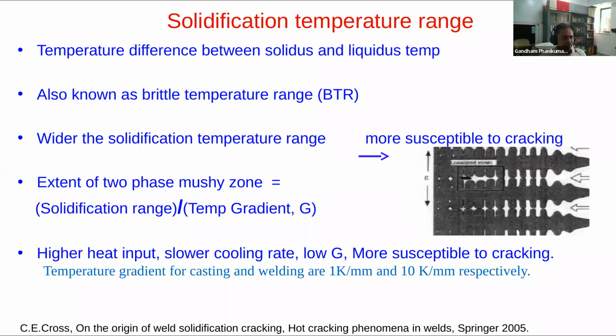Okay, and if you look at the origins of the RDG criteria, they are all talking about how the liquid that is trying to feed the solidifying region is suddenly getting its channel cut off. So that kind of bridging leading to the channel being cut off is the reason why the crack can nucleate, because all metallic materials with the exception of bismuth will shrink upon solidification. So if this much volume of liquid has to shrink, then the liquid has to come from outside to fill the gap, and if it cannot come because of bridging that has happened, that means there's a likelihood of a crack formation. So that is an idea that is overbearing in this concept.